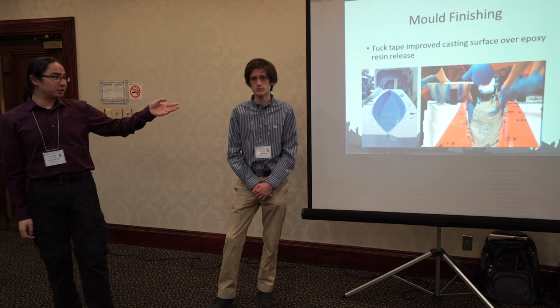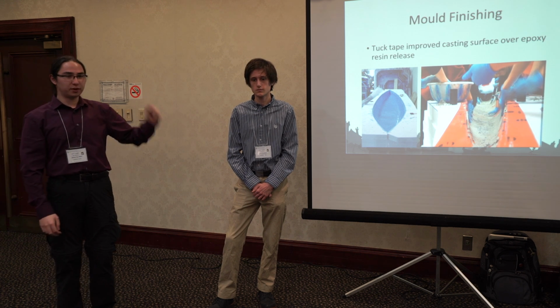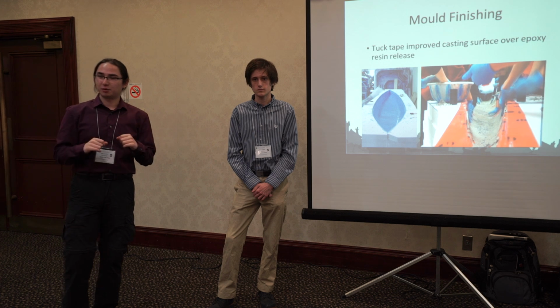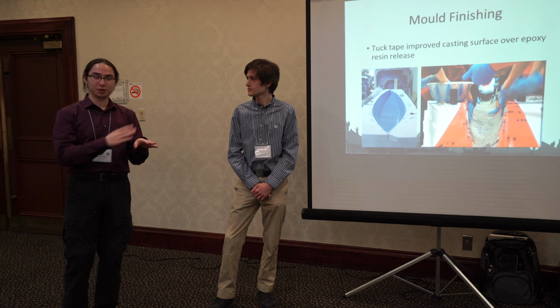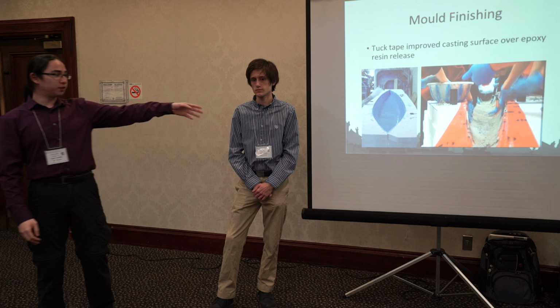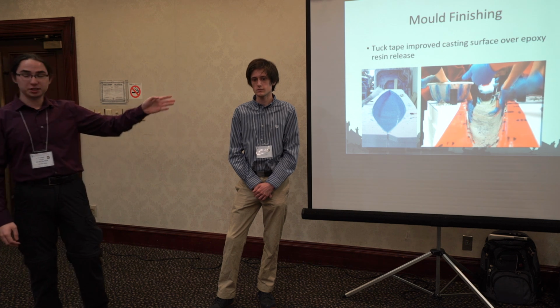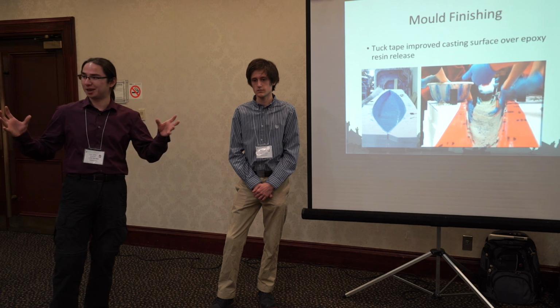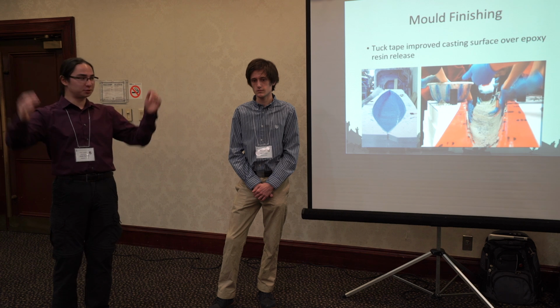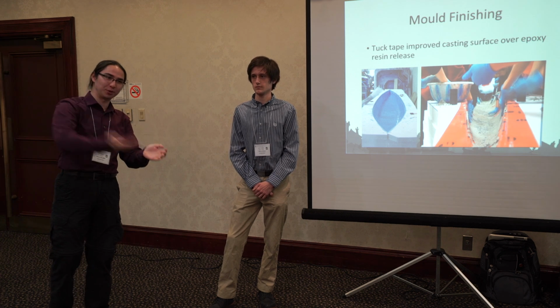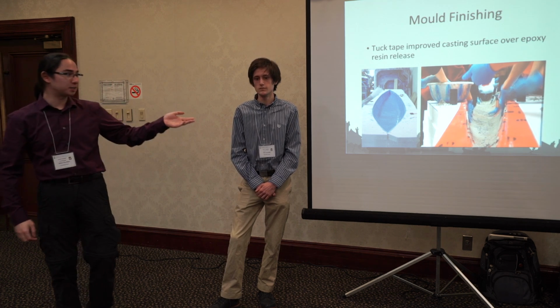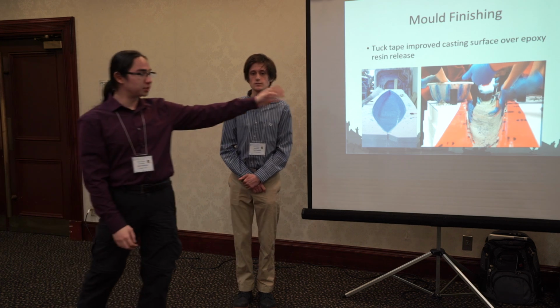So what we found during testing this year is that tuck tape actually works remarkably well at providing a smooth surface that nothing sticks to. So we've switched from the epoxy resin coatings to essentially an all tuck tape coated mold. We just layer tuck tape going along the mold to provide the smooth casting surface, and then we cast upon that, as you can see in the right picture.